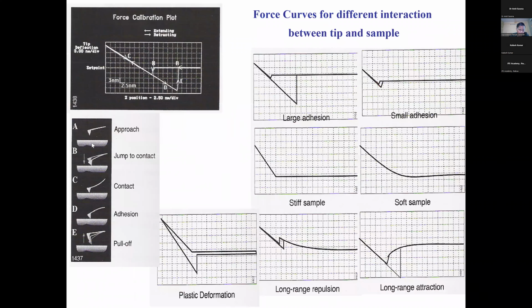Now, what do you do in this? You see the force curve, whatever is happening at the tip. When the approach is at large distances, then when you go nearer to the sample, the sample attracts it. It's a Van der Waals attraction, it jumps to contact. Then after contacting, you try to remove it, it won't move. It is sticking here, so the cantilever will start bending. You apply more force, then it will start coming out, the pull-off. All these things can be seen by measuring the force curves.